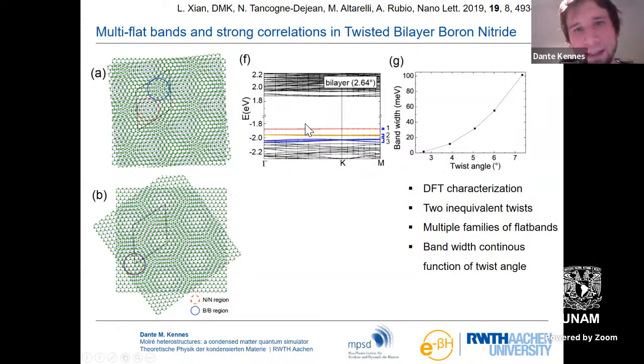But then you see that here, close to the valence band, there are actually families of flat bands emerging. So we have this first band, which is labeled one and highlighted in red. Then we have this small yellow band, and then there's a new band, blue, below it. And all of these flat bands emerge. And we can look, for example, at the bandwidth of this. This is at one given twist angle of 2.64 degrees.